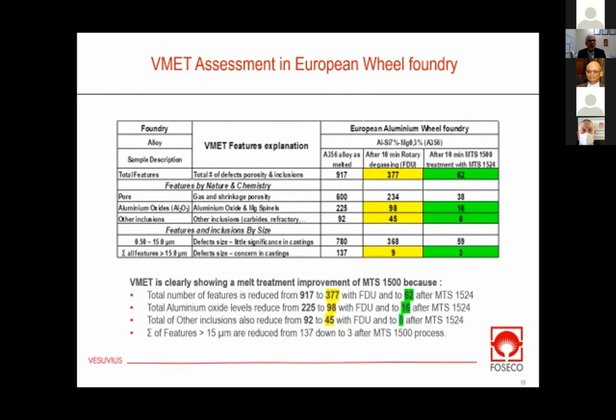Then the foundry has some kind of rotary degassing machine, not using flux, simple rotary degassing. So they process the ladle, and after treating it for 10 minutes, that's the yellow column, we took another sample, did a VMET analysis, and you can see a dramatic reduction in the number of oxides and inclusions found.